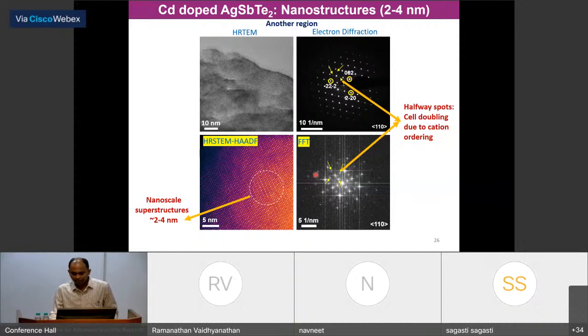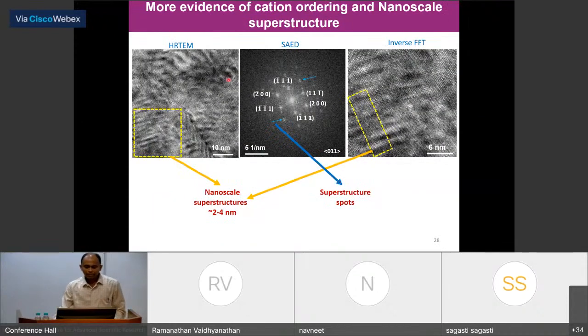And you can see by fast Fourier transform of this image this halfway spot that is coming from the cell doubling. Okay, so then we have done HRTEM experiments in our Titan as well, when it was working, and we see this nanostructure domain with a period of 2 to 4 nanometer, which is a very intriguing discovery, because this size actually matches the mean free path of the phonon in this AgSbTe2. And you can see there is a spot splitting of the fundamental spot. So that means this is a higher order ordering. So that happens due to this 2 to 4 nanometer domain formation.